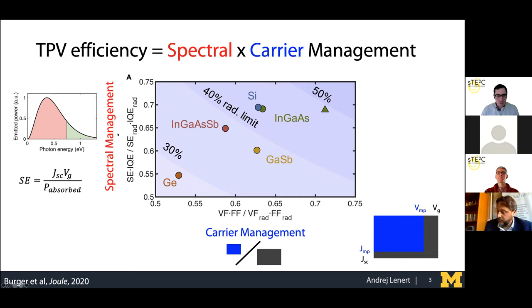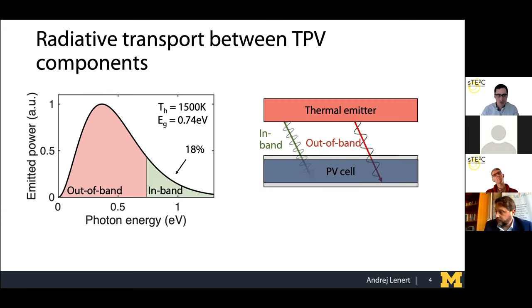So let me jump into how we approach this problem. One of the biggest issues with reaching high efficiency is managing the large amount of power that lies below the band gap. And so we call this out of band radiation. In band radiation at a prototypical temperature of 1500 Kelvin and with an indium gallium arsenide thermal photovoltaic cell, which has a band gap of around 0.74 eV, the in-band radiation only accounts for about 18% of the power. So you can see that the biggest driver in the efficiency is how you manage this out-of-band radiation.